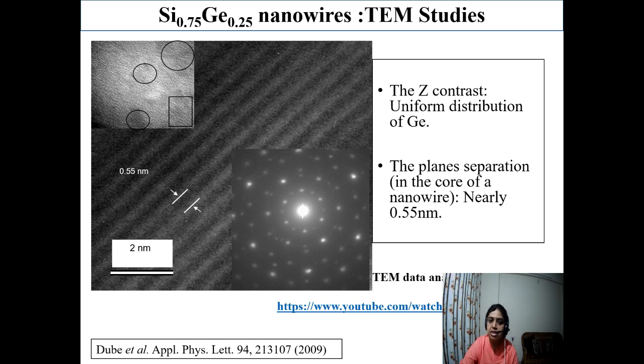Again this SAED pattern is confirming ring pattern. If it is polycrystalline material, then it will be ring pattern. If it is amorphous, then it will be diffuse ring. This ring pattern also can give us a lot of information. If it is kind of amorphous diffuse ring, then it is amorphous, but here you can see it's spotted, it means it is polycrystalline. Now from the phase contrast in the HRTEM, from the fringes we can measure the interplanar spacing. Here you can see 0.55 nanometer. So this is basically the lattice spacing, that is lattice constant of the silicon germanium.